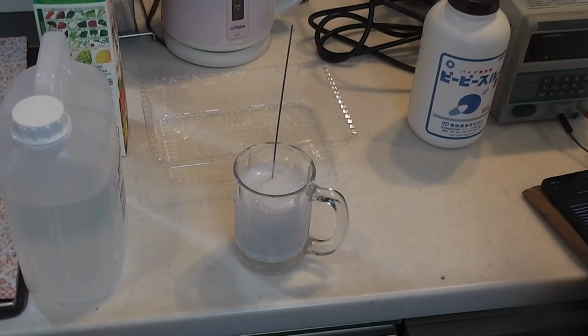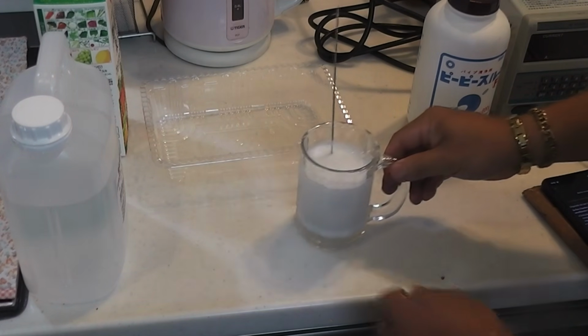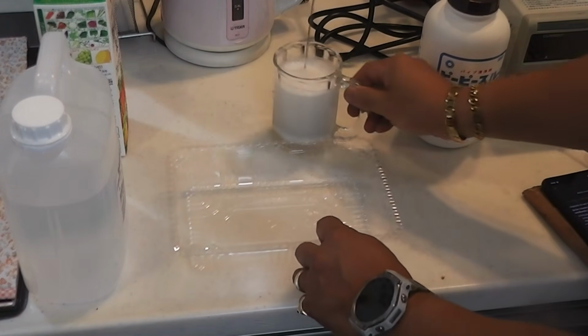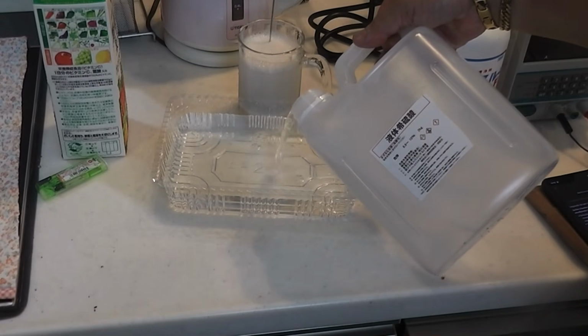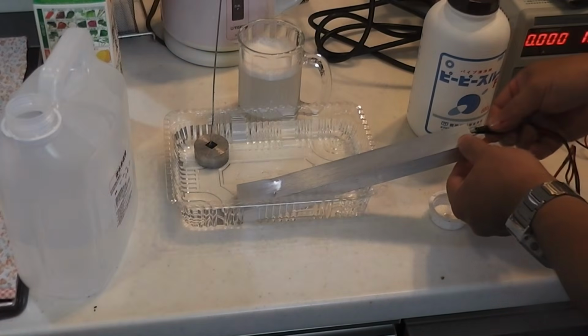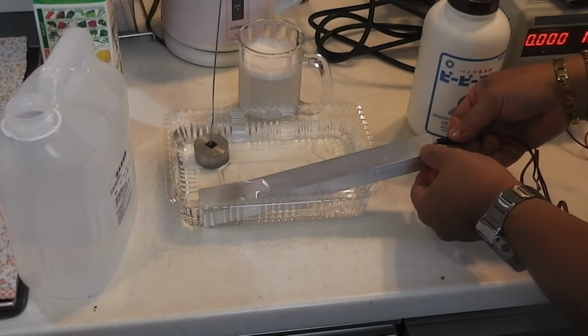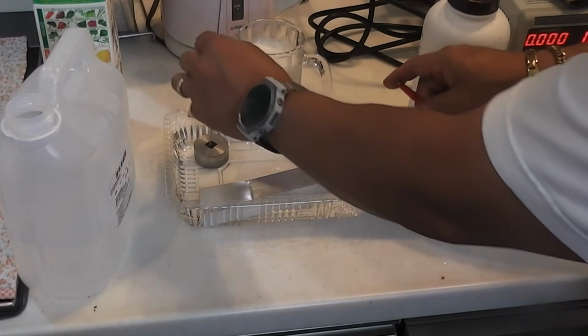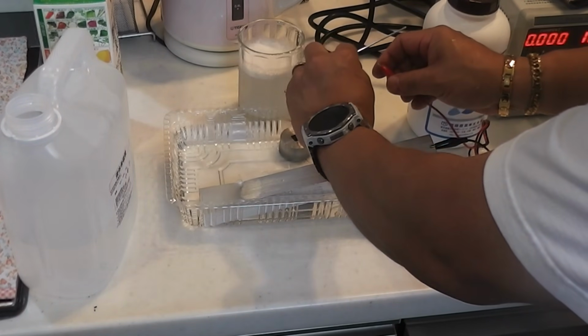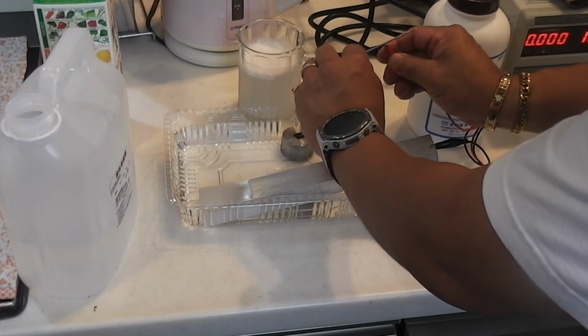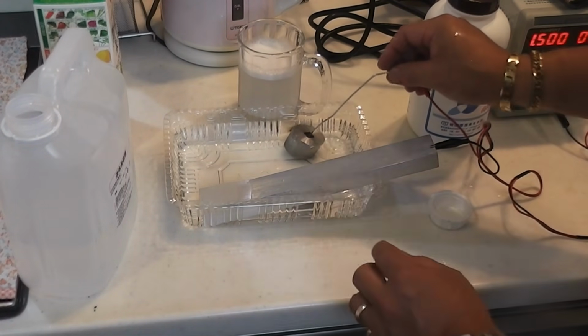Any contamination left behind could prevent the oxide layer from forming evenly and would become visible in the final finish. After the caustic soda bath, the part is thoroughly rinsed with clean water to remove every trace of the solution. Now, it's ready for anodizing. For the electrolyte, I'm using a 10% sulfuric acid solution. The aluminium socket is connected as the anode, which is where the name anodizing comes from. The counter electrode completes the electrical circuit. The power supply is set to 1.5 amps of direct current, and the process runs for 30 minutes.